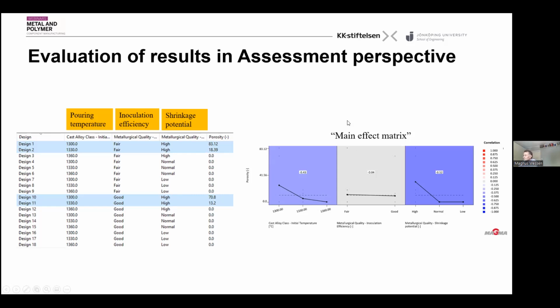Then you can start analyzing this way, but you also have some evaluation tools. We have, for instance, what's called the main effect matrix. Then you can directly see that, in this particular case, when we increase the pouring temperature, the porosity goes down. So we have a quite strong negative correlation, meaning that when this goes up, this goes down. The inoculation also has a similar trend, but very weak. It's not a very strong effect. And the shrinkage potential also has a very strong correlation. So directly from this simulation, you can see we are not in a robust place in the design space. We cannot make sure that we always produce good parts.